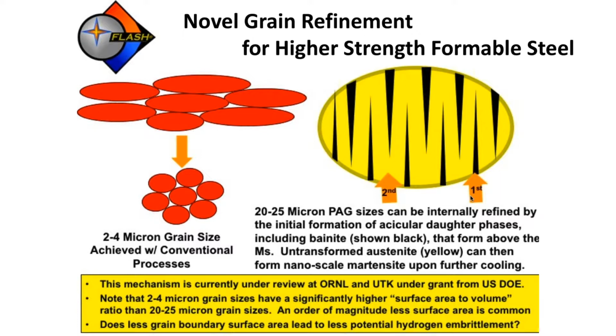What we did very counterintuitively is we actually grew our prior austenite grains up to sizes of 20 to 25 microns. But instead of quenching a homogenized austenite, what we're doing is quenching heterogeneous austenite.